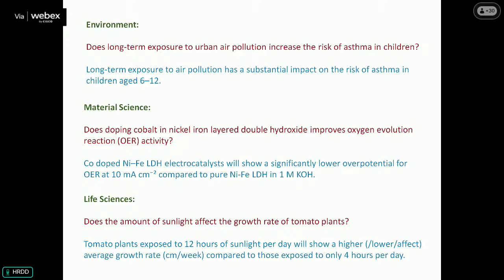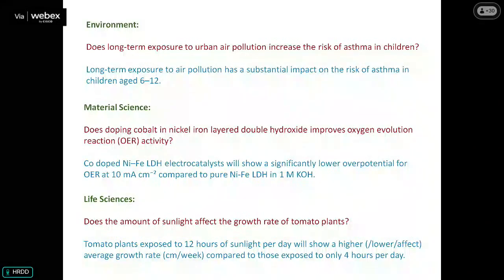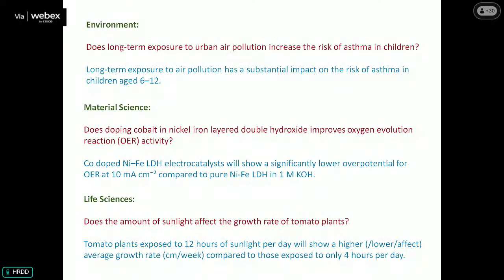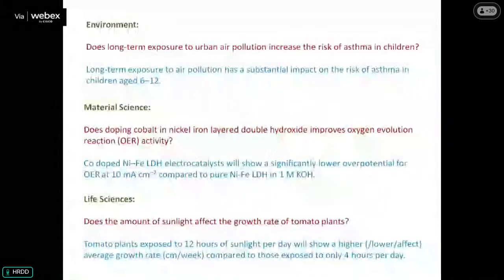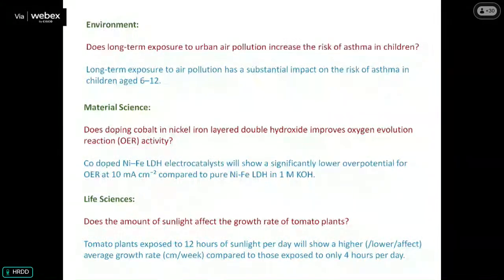All right. But will it increase the activity or not? It has been found that it has increased the activity. So this is what my hypothesis is: the cobalt doping will have a significant impact on OER at 10 milliampere per centimeter square. Then there is no need for research? No, we have to test and prove it, right? And what more we have to do is find the optimum amount of cobalt in the nickel iron layered double hydroxide. Whether 1%, 2%, or 10%, 20%, what is the optimum amount of cobalt to be incorporated so that it improves the activity.